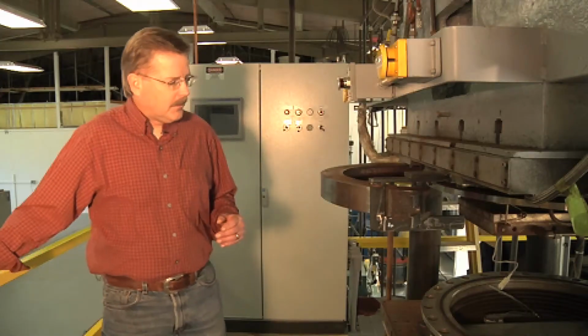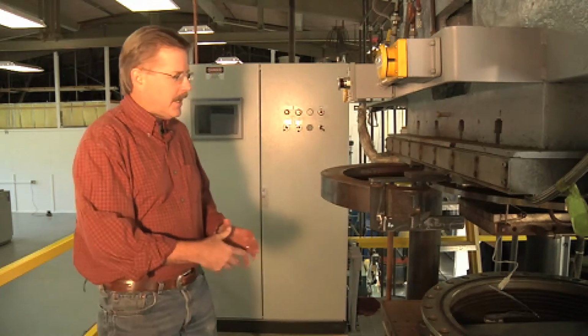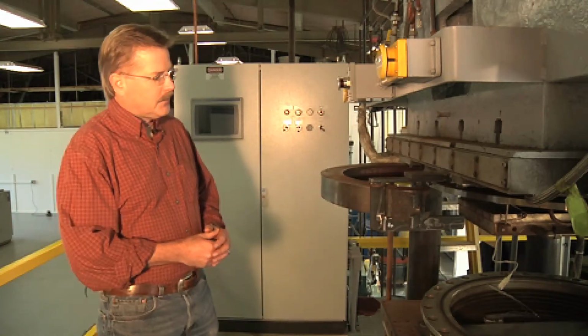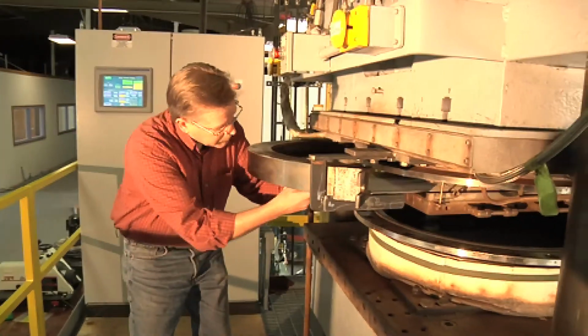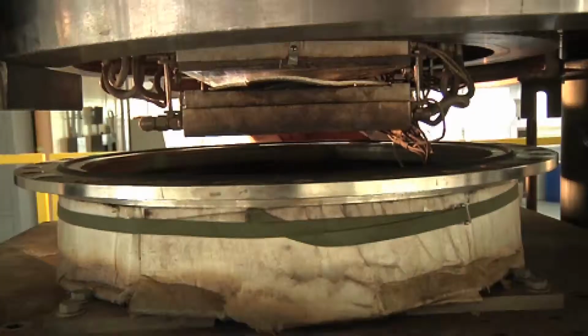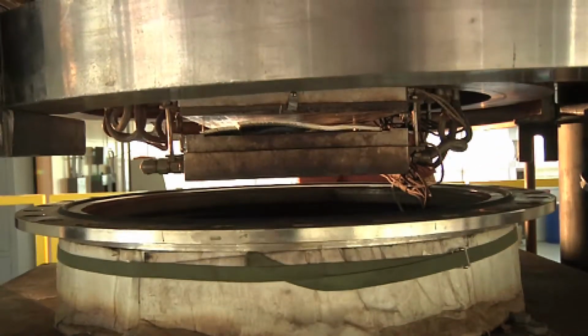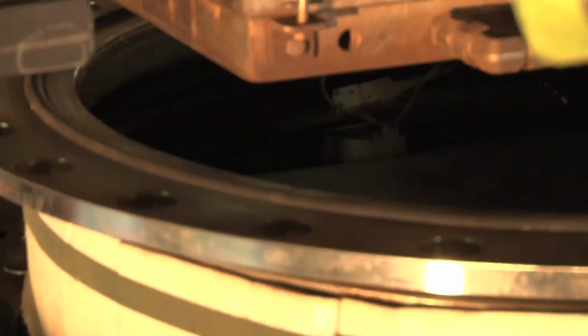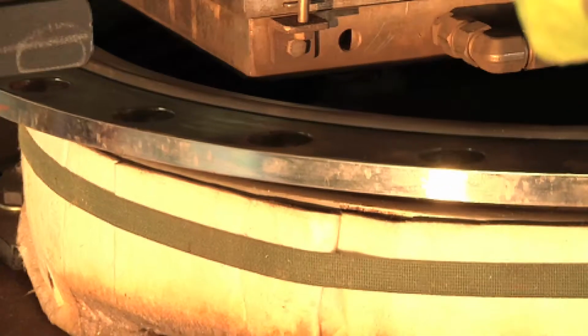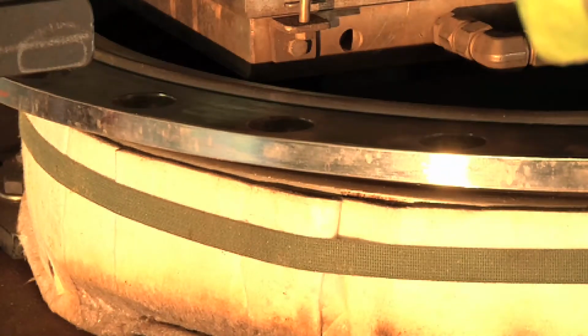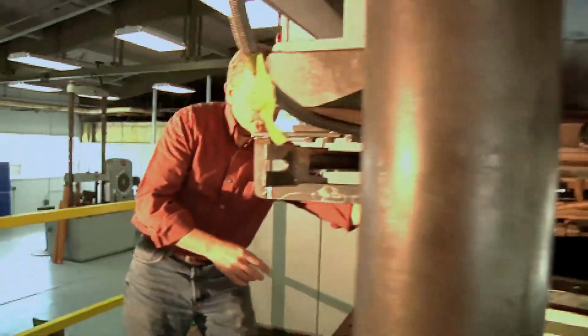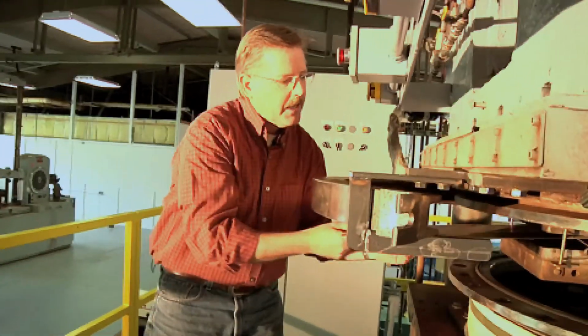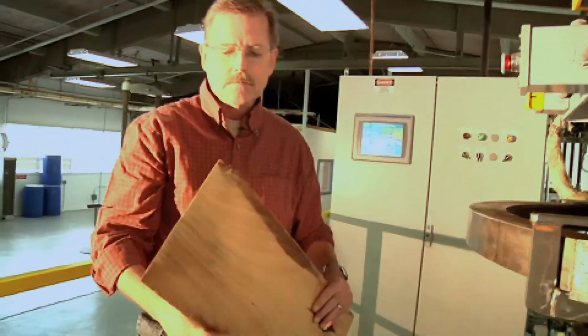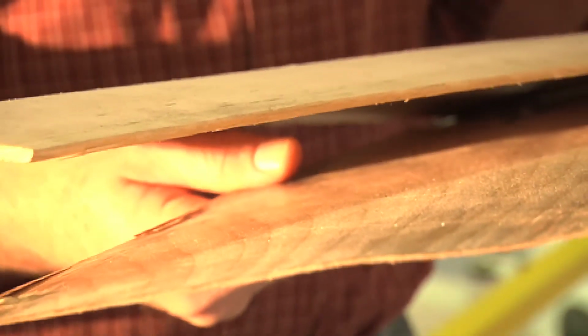This device you see right here has a sealed chamber that's attached to a hydraulic press. This allows us to place the wood inside the chamber, close it up, and then subject it to pressurized steam prior to applying a compression force to increase the density. We literally crush the wood, but we crush it without causing fractures in the cell wall structure. At the end of the process, the wood has been cooled down below 100 degrees C, and the density has been increased. Typically, the density increase will be about 3 to perhaps 4 times denser than the initial density of the wood when we put it in there.